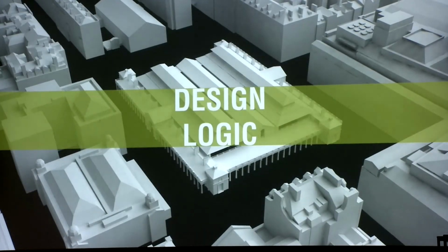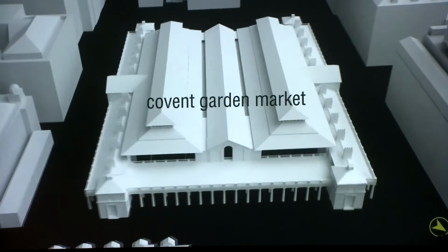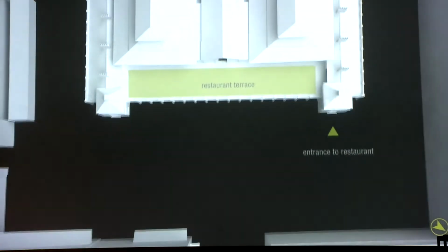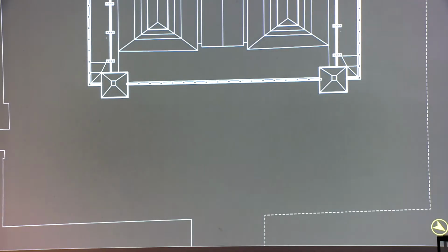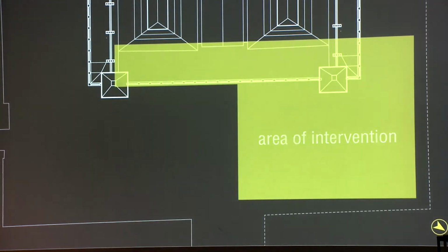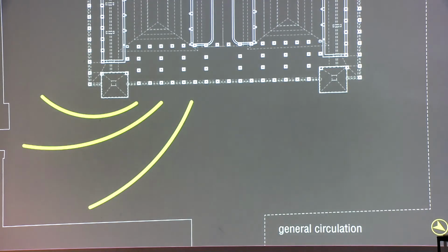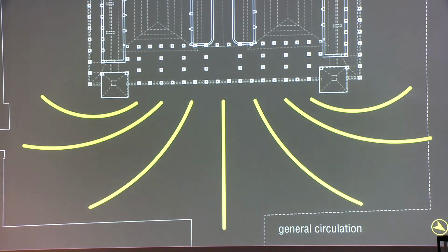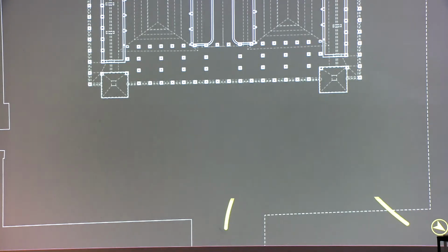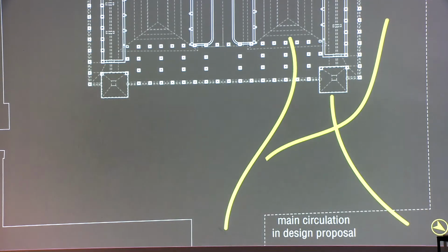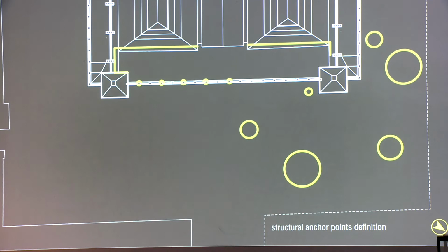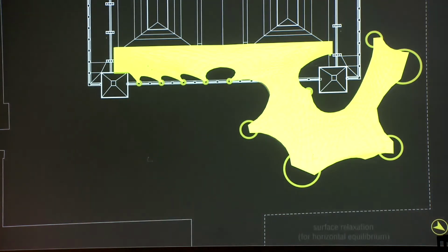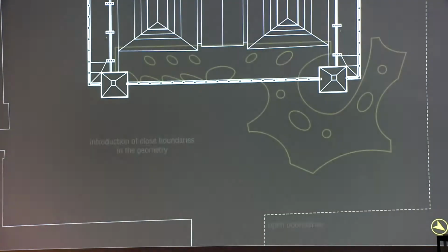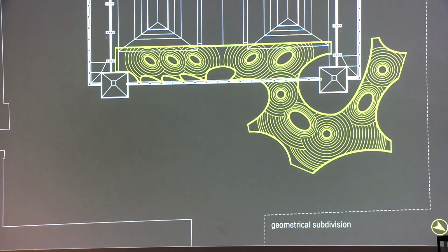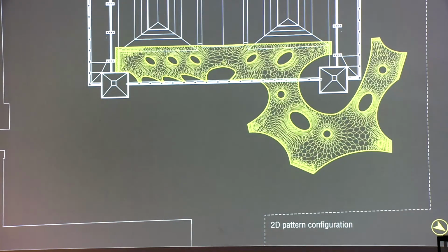We generated a prototypical application of our system on a restaurant in the Covent Garden Market in front of Russell Street. In order to generate a relation with the Opera House building, we extended the design area from the terrace to the square. We took into consideration the main circulation that happens in the square, and we focused our attention on the circulation that affects our design area. According to this circulation, we defined anchor points that we use to define the boundary and the opening edge of our geometry. We introduced closed boundaries that generate new anchor points, and we generated a circular pattern that gives us control over the length and the density distribution of nodes, generating the 2D initial pattern.